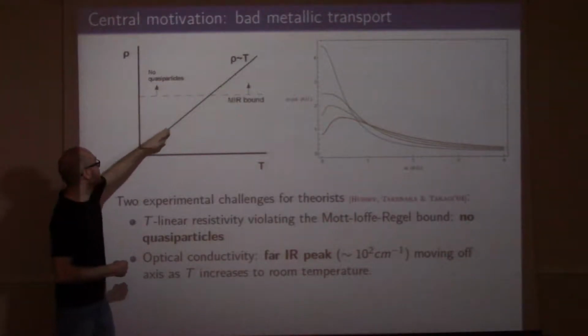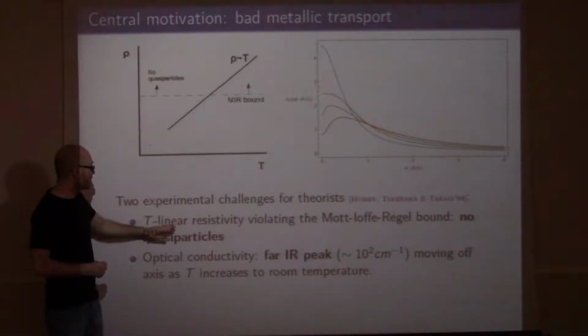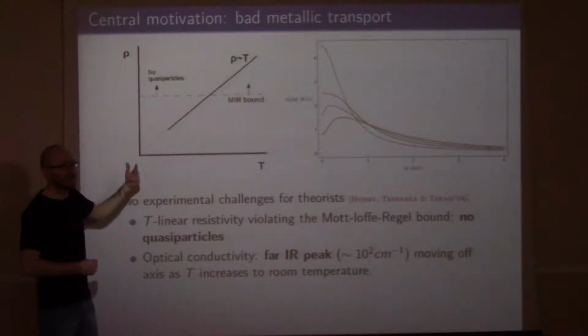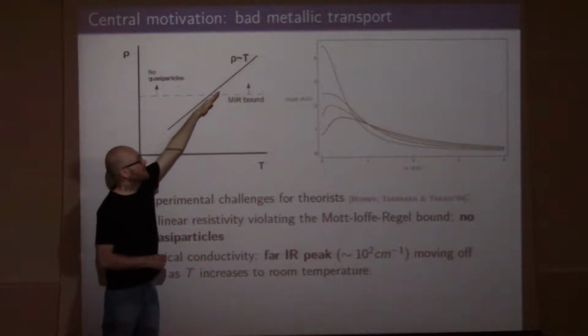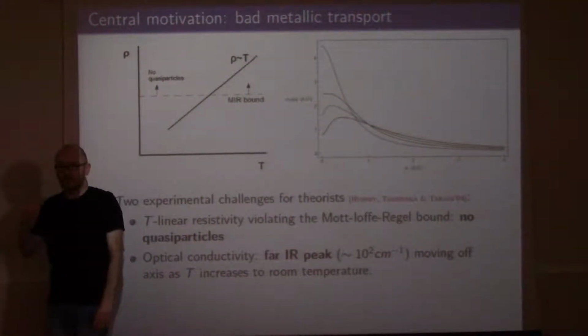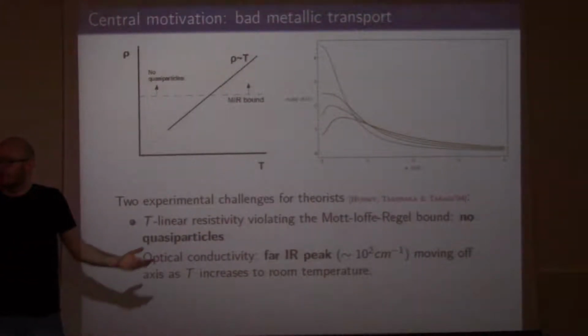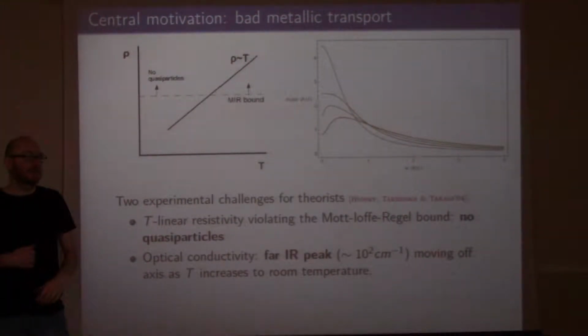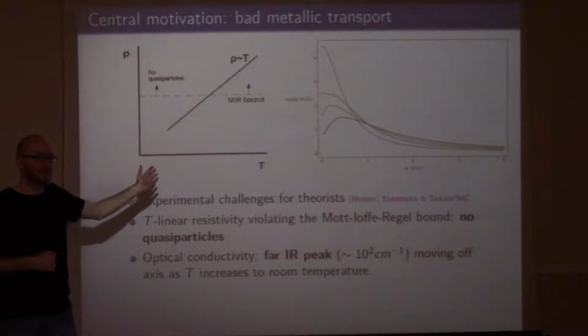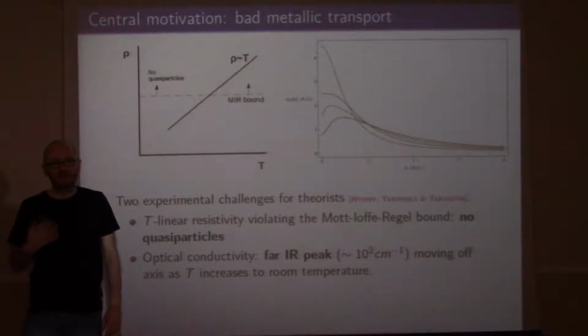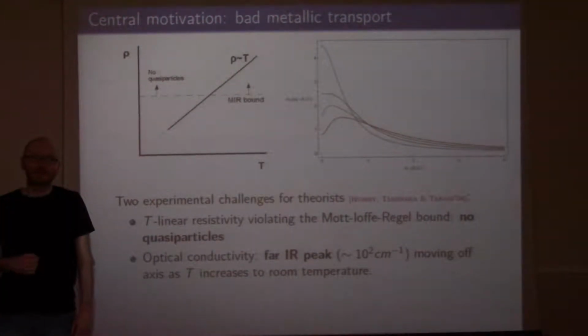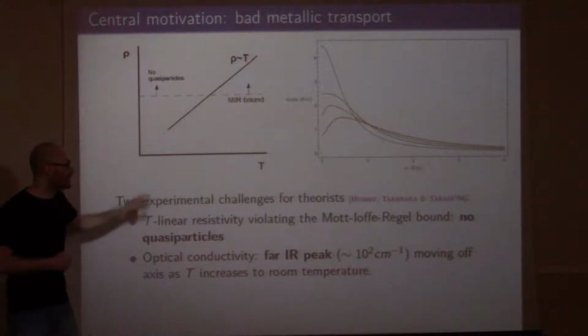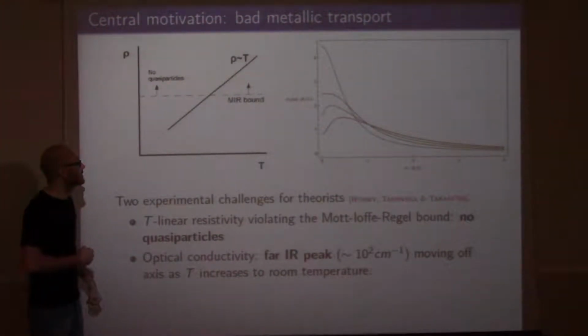And as you can see from this schematic, essentially for all these bad metals, and there are many of them, we've discovered many of them, the resistivity just crosses this bound. So the crossing of the bound tells you that the quasi-particles cannot be responsible for transport in these systems. So you have to think of something else. This is a sign that these systems are strongly coupled, essentially. So that's one puzzle that has to do with DC transport.